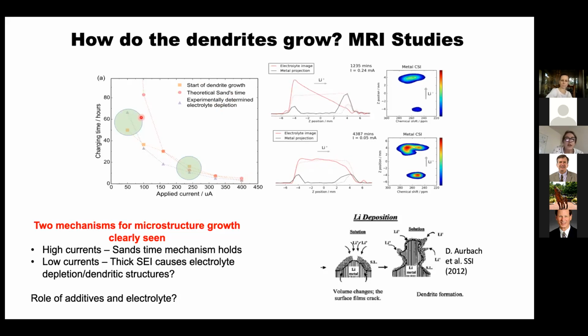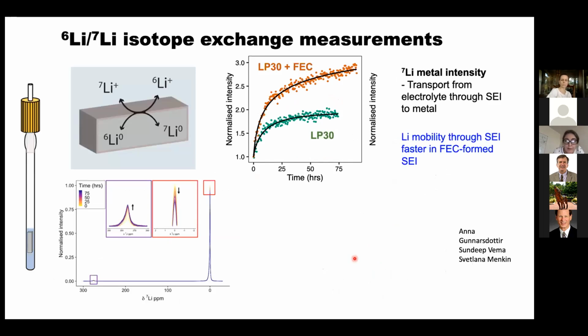But at low currents, in principle, you should be able to get to a regime that's shown here, where you don't actually get a 0 concentration of electrolytes, but you still start to see dendrites. And the reason for that, sadly, because if this didn't happen, it would mean you could just back off in the current and you still have no problem, is this passivating layer that forms. And because this passivating layer is cracking and is not very homogeneous, as the dendrite grows or the film grows, you can get regions where you get high electric fields, and you can get dendritic structures. And so the challenge now is to think about what that passivating layer looks like to control it. And so that's what we've been focusing on in the last few years.